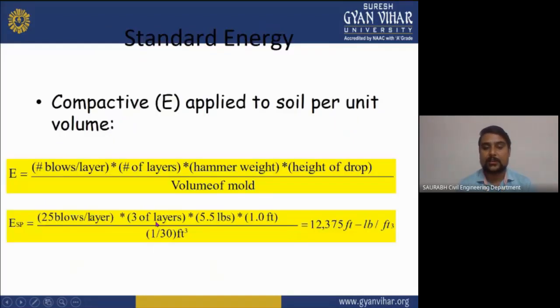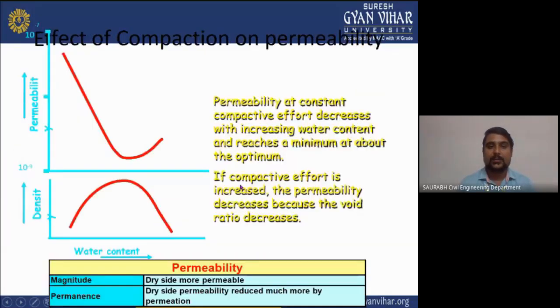Here you can see this is your graph which is showing the structure of compacted clay, and this is the effect of the compaction on permeability. This graph is showing the effect of the compaction on the permeability. At constant compaction effort, permeability decreases when water content increases and reaches a minimum at about the optimum. If compactive effort is increased, the permeability decreases because the void ratio decreases. This is the graph which is showing the relationship between water content and density and water content and permeability.